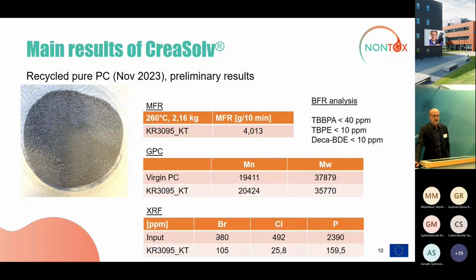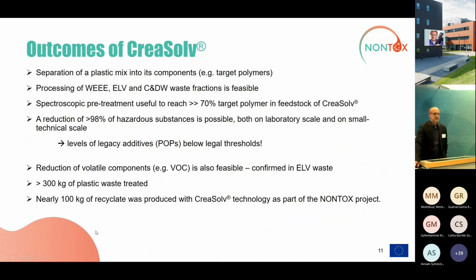And you see the rate of reduction was not as high as usual, since we didn't go too deep into extraction, since we evaluated the resulting residues of bromine, chlorine, and phosphorus below 200 ppm as sufficiently clean. Okay, outcomes. To sum up very shortly, we could show that it's possible to separate ABS, PS, and PC ABS from plastic mixtures into its single components. We could process these and isolate these plastics out of WEEE, ELV, and C and DW waste fractions.